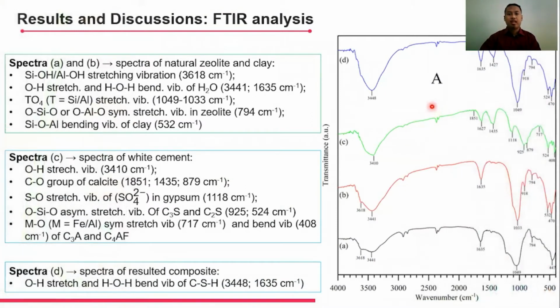Ladies and gentlemen, you can see the infrared spectra of natural zeolite, natural clay, white cement and the prepared composite in figure A. Spectra A and B refer to infrared spectra of natural zeolite and clay. From these spectra, we get information about silanol or aluminol stretching vibration, then hydroxy stretching and HOH bending vibration of water molecule in zeolite clay, TO4 stretching vibration, and then OSiO or OAlO symmetrical stretching vibration in zeolite, and the last is SiOAl bending vibration of clay.